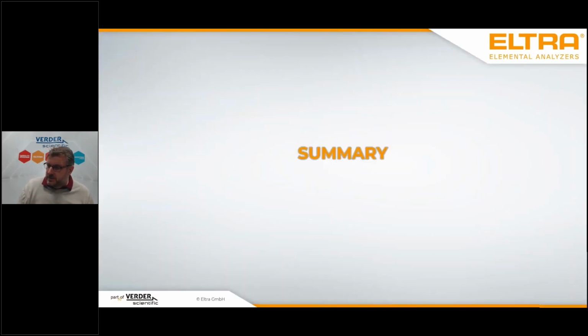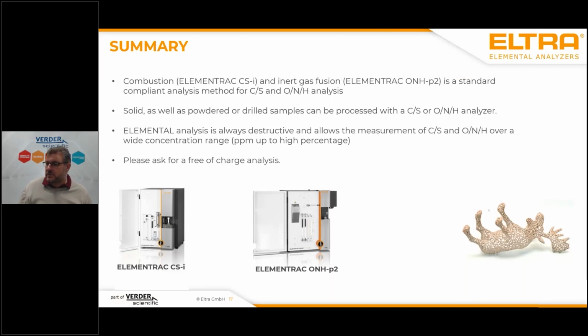Yes, and this is the reason why I can come now to a summary, because in detail it may be a little bit different what you have to do for your samples, and details you have to consider, because sometimes we get powdered samples which are maybe based on rare earth materials, or maybe you have very cost-intensive samples like silver or gold, and there you sometimes have to consider other details. But in sum, you take your sample, combust it in an analyzer, and measure the released gases. And this is the same for solid samples, powdered samples, drilled samples. And it also does not matter if you have a titanium-based sample or an iron or nickel-based sample. We are always doing the same, but maybe sometimes we have to consider a lot of small details.